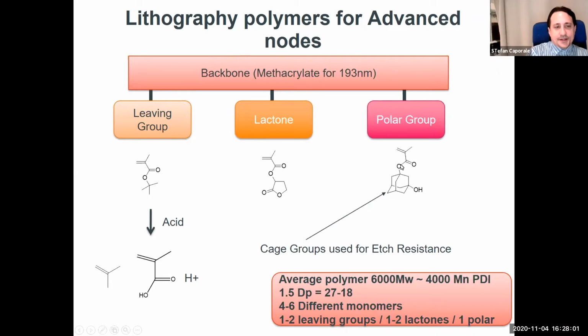And then there's normally a cage polar and/or functionalized monomer that has, again, these adamantyl cages have a very high carbon to hydrogen ratio, which allows very good etch resistance. And then again, we can functionalize off these cages hydroxyls to give adhesion or other functionality as needed to tune the material. These are very unique polymers because we normally combine 4 to 6 different monomers. So I spent years learning how to and studying the reactivity of these and knowing how to put them together correctly and control that reactivity of them.